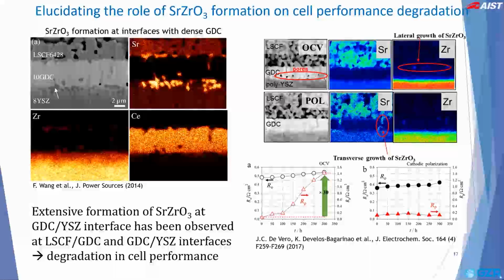On the right-hand side is another related study which showed that after cell tests, strontium zirconate formed at the LSCF GDC interface as a result of extensive zirconium migration in the PLD-grown GDC interlayers. The lateral growth of strontium zirconate along the LSCF GDC interface is accompanied by a remarkable increase in the polarization resistance with operation time, especially under open circuit voltage condition. It is therefore clear that the strontium zirconate formation drives the rapid degradation of the cell performance with time.